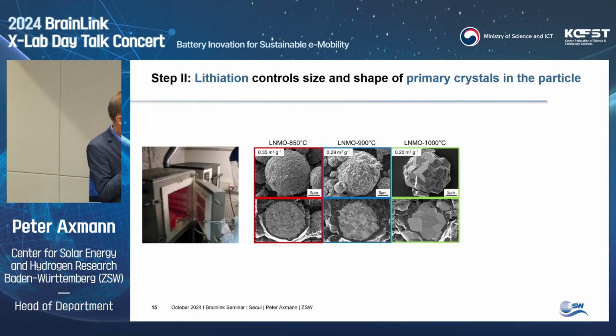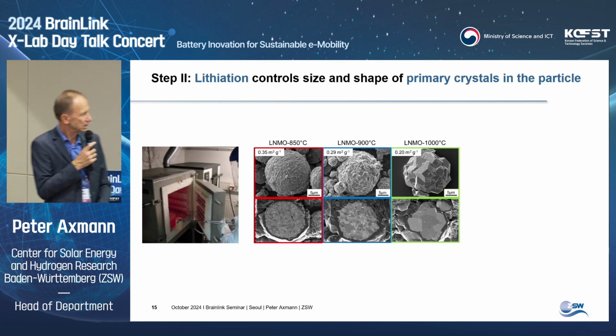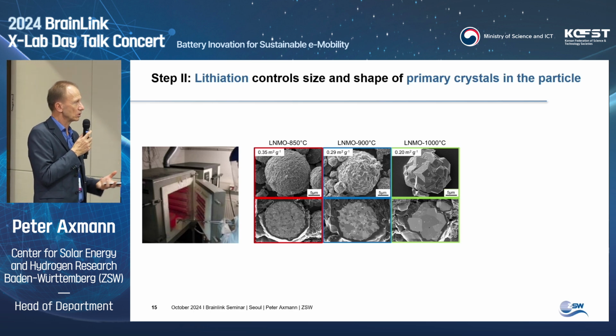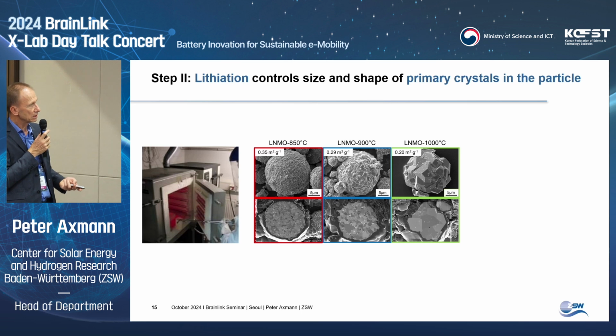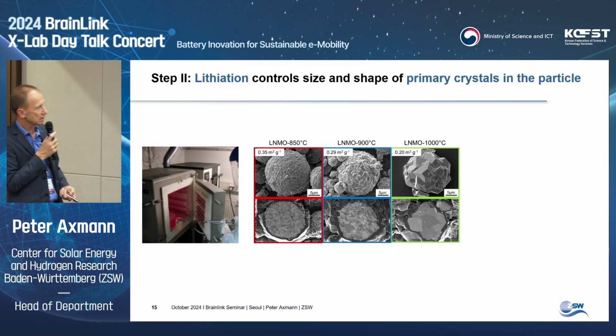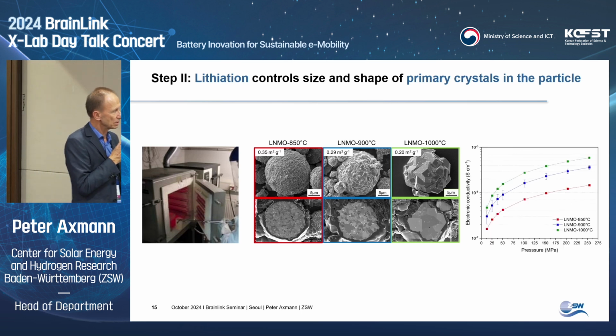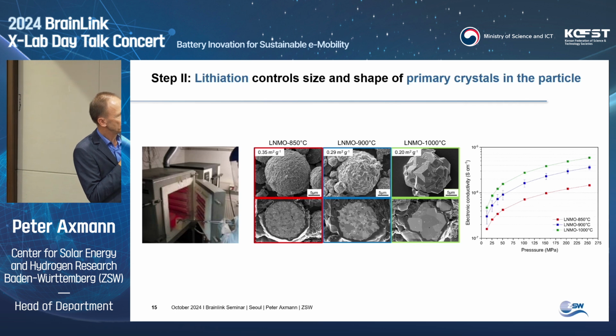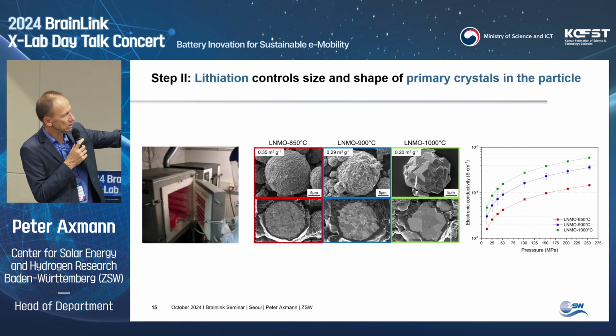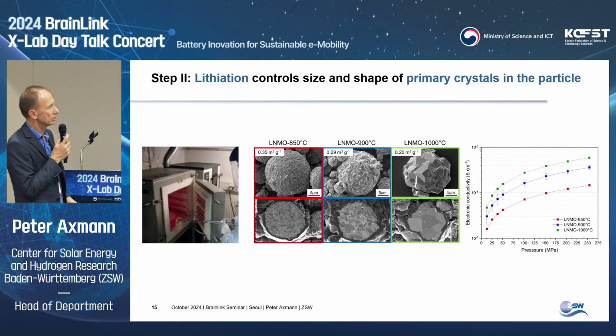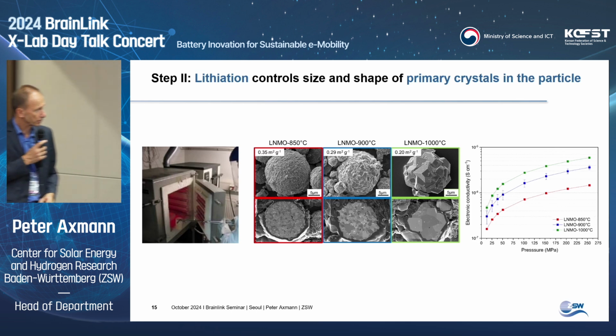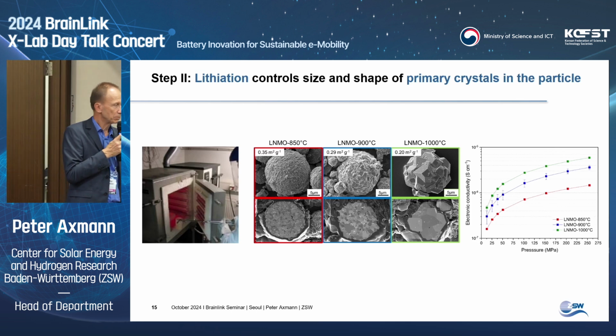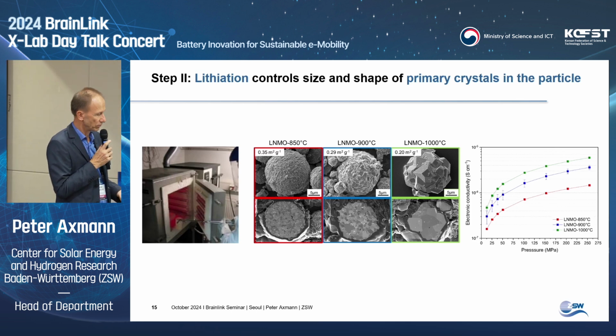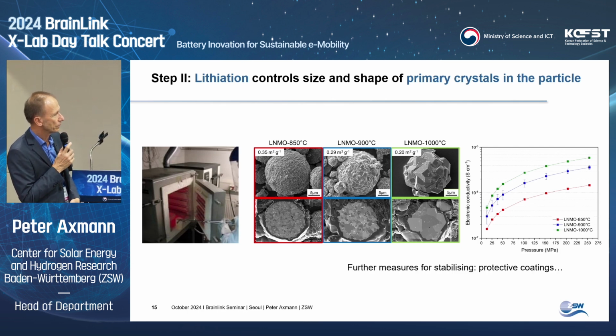Here you see it in the cross-sectional view very nicely below. And this, of course, has an influence on different things: on density, on surface, on side reactions. Here's something on the powder conductivity we measured for these types of materials. It drastically goes up for the materials made at higher temperature. And this is, of course, important for the rate capability, to have good conducting materials.